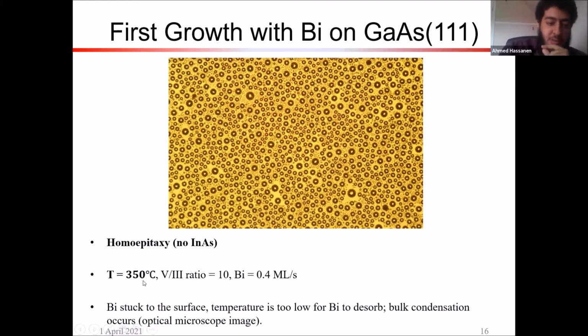And so what happened here is that we used a temperature of around 350 Celsius. And what we saw here is that bismuth actually stuck to the surface. The temperature is too low for bismuth to evaporate or dissolve. The desorption is heavily dependent on the temperature. And so what happened was this bulk condensation. So we just got a huge layer of bismuth, on the order of microns. And even the substrate was white. So this is the optical microscope image. And so, well, that's not going to work. We're going to have to change something about the temperature.